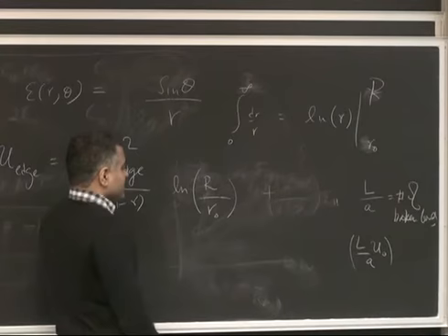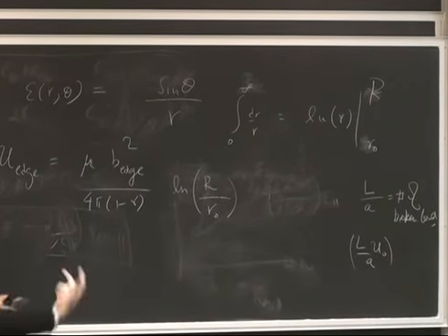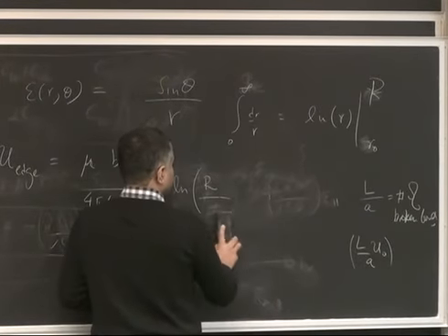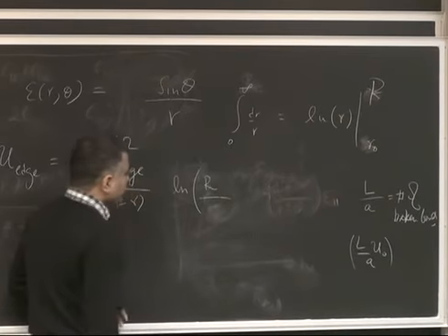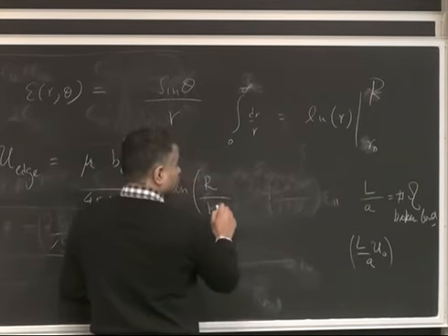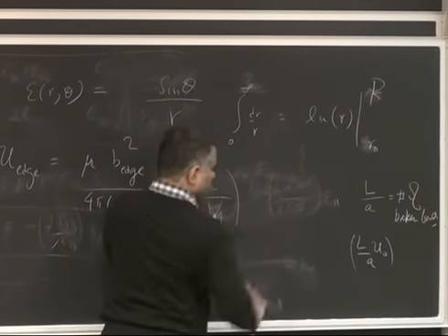And so you can do that, but then typically what is done, and what is found, is that if you cut off the lower length at roughly Burgers vector over 4, I'm just saying, Burgers vector over 4, then it accounts for that energy already.